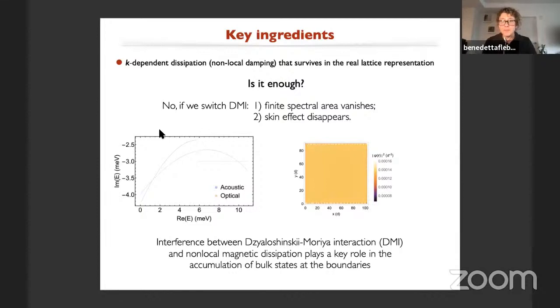But is this enough? If we switch off DMI, we find that no matter if there is non-local dissipation in the system, our finite spectral area vanishes and the skin effect disappears. From a mathematical standpoint, you can realize that by noticing that in the absence of DMI, the imaginary part of the energy becomes a function of the real part of the energy, and therefore it must be a line in the complex energy spectrum.